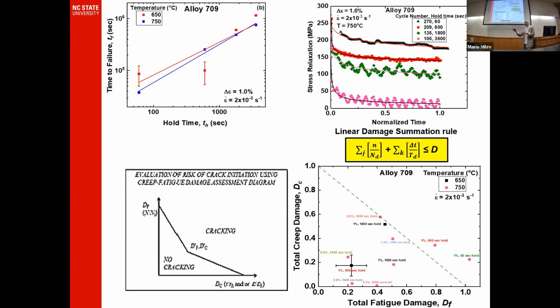Transgranular cracks interact with intergranular cracks, and the material fails. Higher values of creep damage mean that cavitation damage is enhanced by cyclic loading.